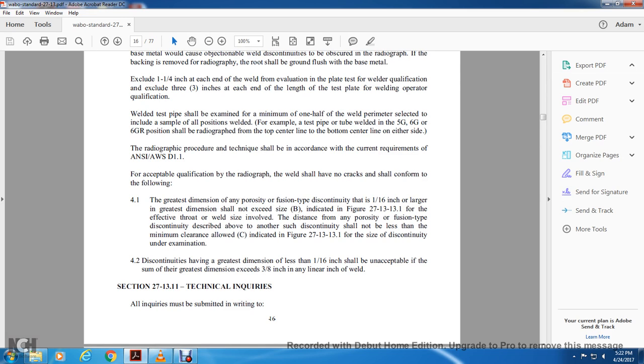The greatest dimension of any porosity or fusion type discontinuity 1/16 inch or larger in the greatest dimension shall not exceed size B, indicated in Figure 2713.13.1. For the effective throat and weld size involved, the distance between any porosity or fusion type discontinuity and any other such discontinuity shall not be less than the minimum clearance allowed in C, indicated in Figure 2713.13.1, measured from the side of the discontinuity under examination. Discontinuities having greatest dimensions of less than 1/16 inch shall be unacceptable if the sum of the greatest dimensions exceeds 3/8 of an inch in a linear inch of the weld.